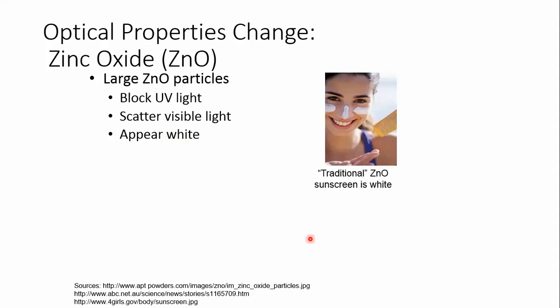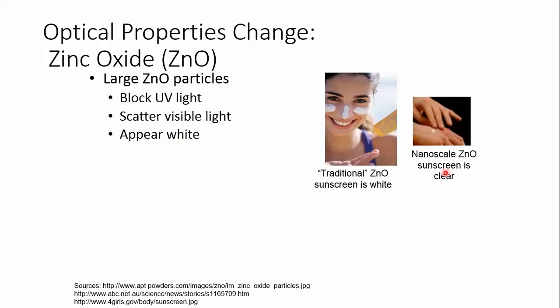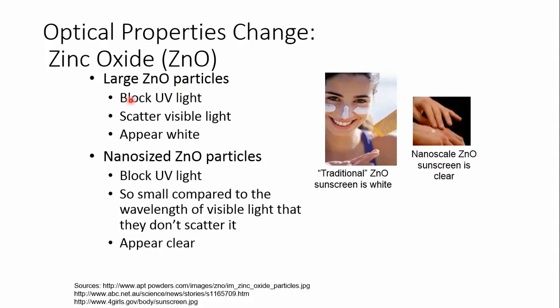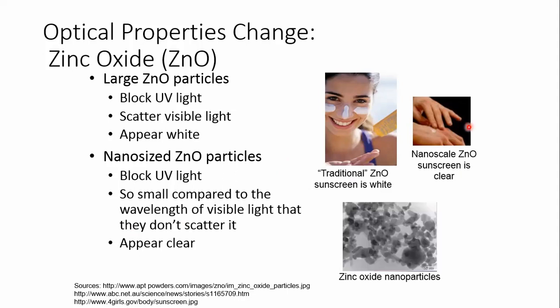But with the development of nanotechnology, now this is nanoscale zinc oxide sunscreen, which is clear. At the nanoscale it is still doing the UV light protection, but the particles are so small compared to the wavelength of visible light that they don't scatter and appear clear. So when you change the size of the same zinc oxide particles, here it was white and now it is clear. The optical properties have changed, but the other chemical and physical properties are the same. These are the zinc oxide nanoparticles, a TEM photograph is shown here. Some scale is given, 30 or 50 nanometers, so these are of that size.